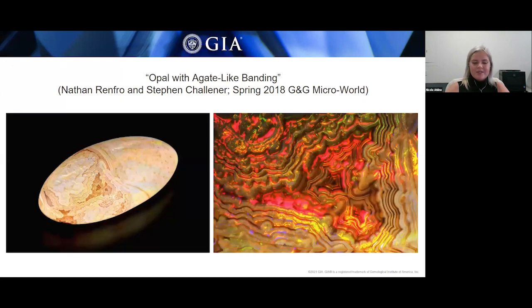So the last opal we'll discuss is again from Ethiopia, and this displayed an unusual growth structure. A portion of the opal displayed a wavy layered banding, much like one would see in an agate. The banded area seen in the photomicrograph on your right was composed of two layers. One was a harder, translucent, dark brown material with no play of color, alternating with a lighter opaque material that did show play of color. That lighter area also absorbed water, which classified it as a hydrophane opal.